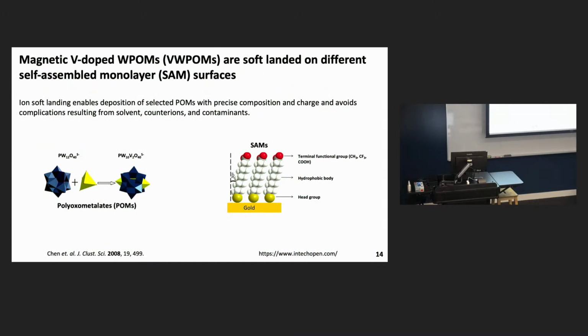So the first thing we needed to do was make one of these vanadium-doped polyoxometalates, as shown on the left-hand side. That's fairly easy to do through substitution in solution. Then we needed a surface where we could change the functionality that the cluster interacts with to see what effect that has on the vibrational properties. For that, we picked self-assembled monolayers. These are easy to make on gold. They have well-defined structure and functionality, and you can change the terminal functionality from, say, methyl to CF3 to carboxylic acid. This gives you a way to look at how specific interactions with those deposited clusters affect their vibrational modes.